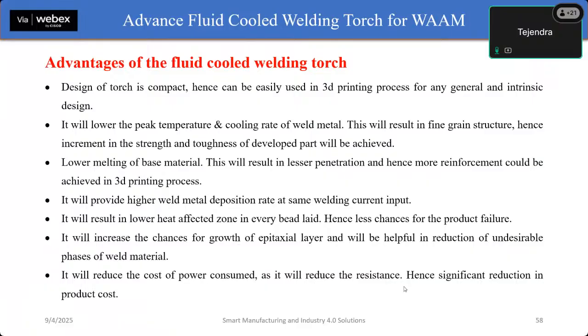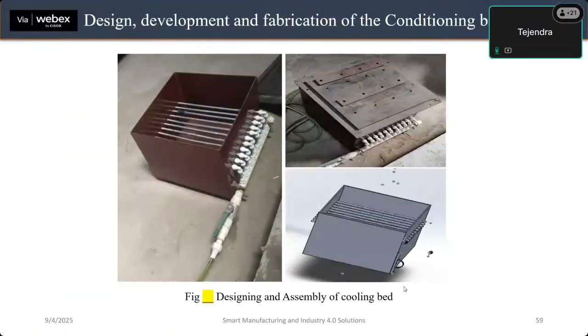It will provide a higher weld metal deposition rate at the same welding current input. It will result in a lower heat affected zone, hence less chance of failure of the weldment. It also reduces the cost of power consumed, as it reduces the resistance. This we are going to discuss in our further slides.